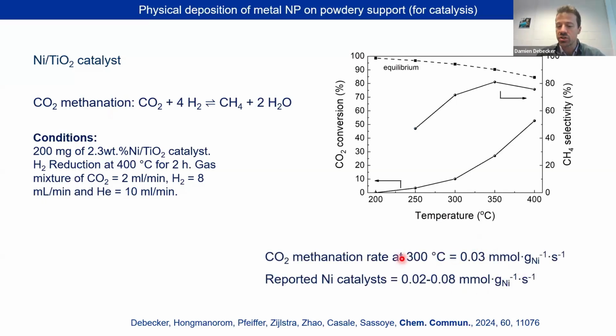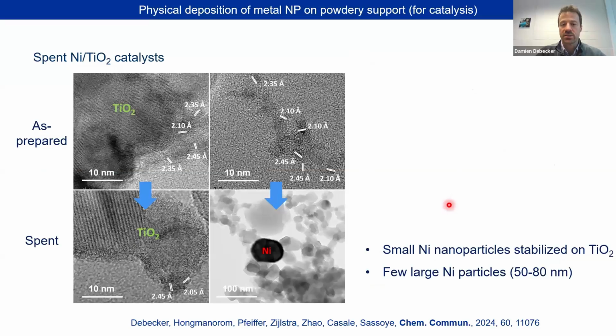They fall in the range that we typically find for nickel-based catalysts, as you can see there, as expected. If we analyze the spent catalyst, we see that it still contains a lot of tiny nickel particles attached to the titania support. So that's what we want.